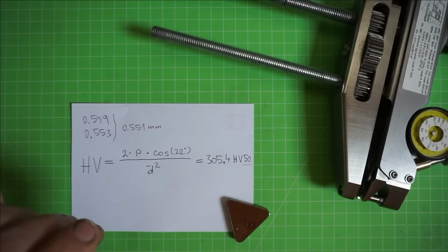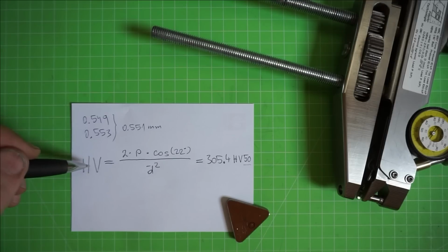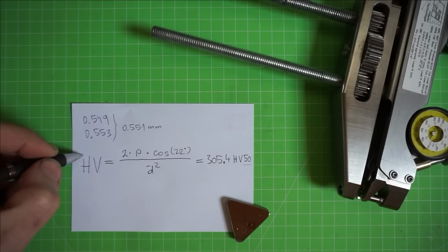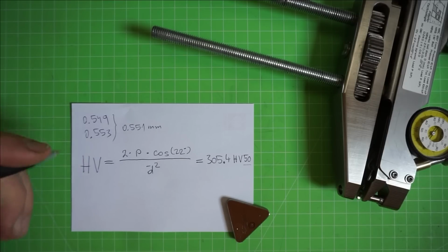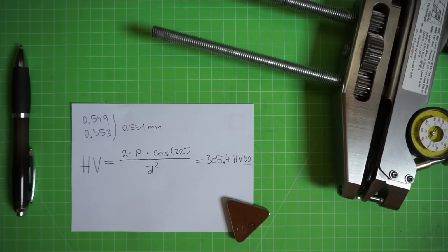And this has to be checked always when you do the Brinell test, and this is something that you don't have to do with the Vickers test. This is why I consider the Vickers hardness test the most universal one, even if it's not the most established one, but the most universal one in my opinion.